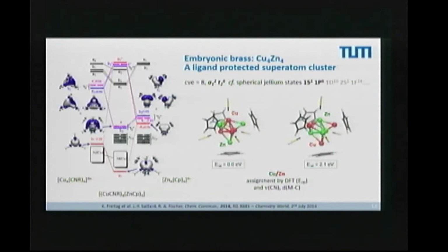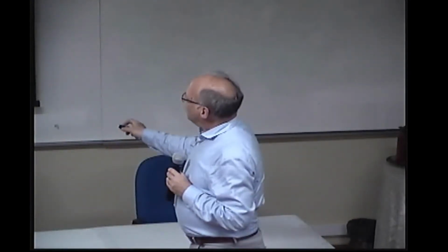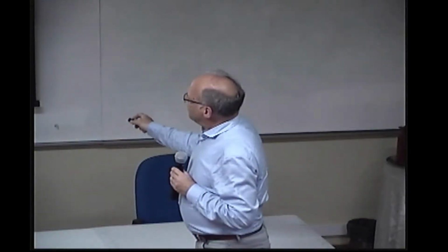Now, if we invert the situation, when you say, okay, let's put the zinc inside and the copper outside, let's put the Cp* to the copper and the isonitrile to the zinc. This is also a structure which you can calculate. It's theoretically completely okay, but it's 2.1 electron volt above the minimum. And from the stomach feeling of the organometallic chemist, this makes an awful lot of sense, because in metaphoric language, the isonitrile ligand is a soft binding ligand, and the copper is a soft center, so from the hard and soft acid and base principle, the soft ligand goes to the soft center, the Cp* is a harder ligand, it goes to the harder center, and this is nicely shown here. Okay, so if we have 8 atoms, 4 coppers, 4 zincs, we have this tetrahedron in the tetrahedron, and we have the copper inside and the zinc outside.